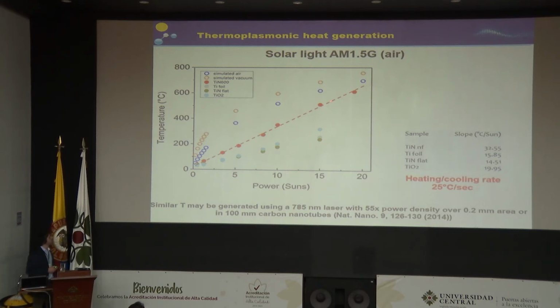As we can see, our materials really outperform reference materials such as titanium foil or titanium oxide cavities. And remarkably, with very moderately concentrated solar power, we can achieve temperatures above 600 degrees C. This is quite interesting because, for example, solar thermal technologies like solar towers reach this temperature by using two orders of magnitude higher concentrated solar power. This means that we can use surface plasmons to develop a new generation of solar thermal technology to concentrate light and do something useful. Of course, I can skip this.